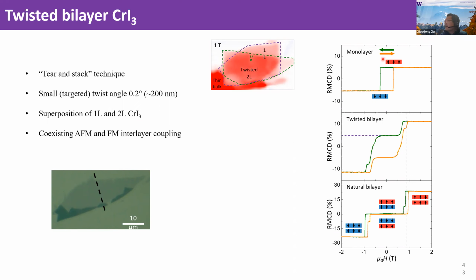This resembles a natural monolayer, but it's a twisted bilayer. At the same time, we also see a spin flip transition at a higher field than the monolayer, consistent with the bilayer. So just by looking at this data, it tells me the twisted bilayer behaves like a mixture of a monolayer and a natural bilayer.